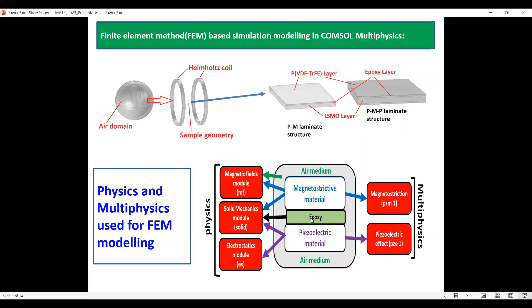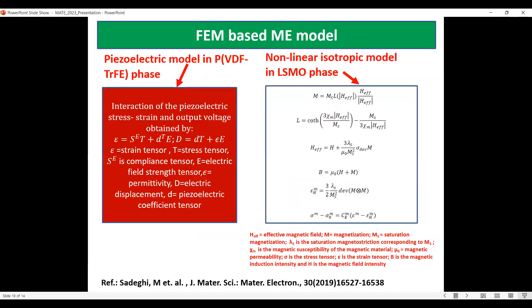To handle this physics, we use two multiphysics couplings: magnetostriction and the piezoelectric effect. The piezoelectric modeling for the PVDF-TrFE phase is given by two linear constitutive equations of piezoelectricity: strain is related to stress and electric field, and the electric displacement vector is related to the stress tensor and electric field vector.